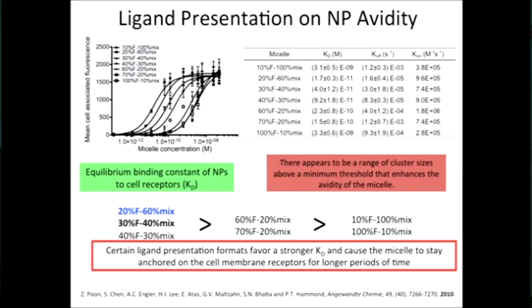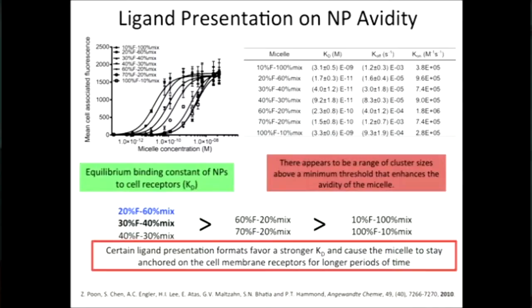And to measure how strongly these bind, for each of these micellar systems, we measured the KD, the dissociation constant. And in this case, we're looking for a very small number. When we look at the 10% folate, we see that we're getting 10 to the minus ninth. We're at nanomolar. That's great. That's very good binding. But what we find is that if we go to 20%, which is on average about three to four of these folates in a cluster, we see that we get two orders of magnitude change in that binding avidity, from 10 to the minus 9th to 10 to the minus 11. So essentially, we're getting 100 times better binding in these systems.